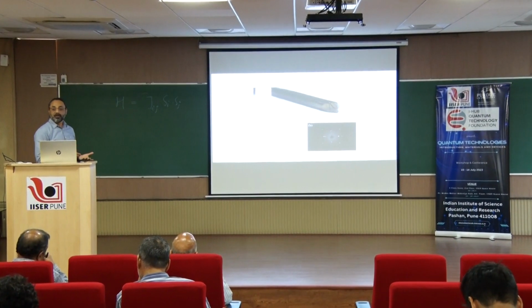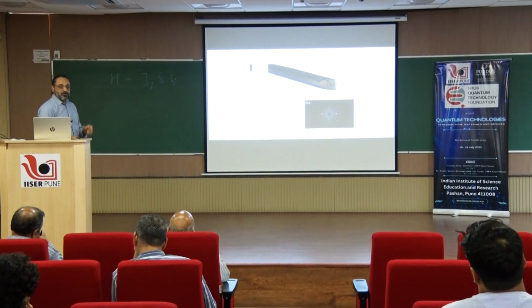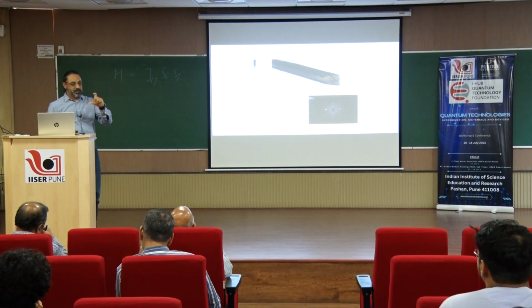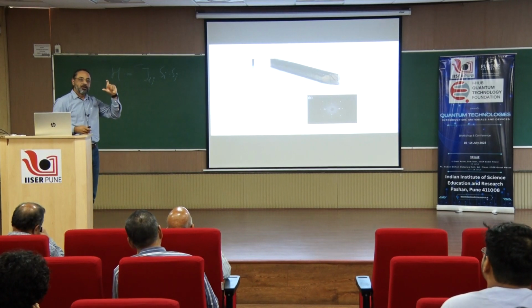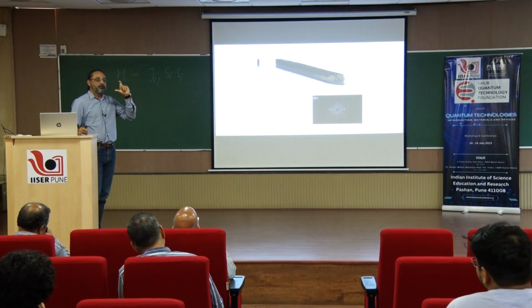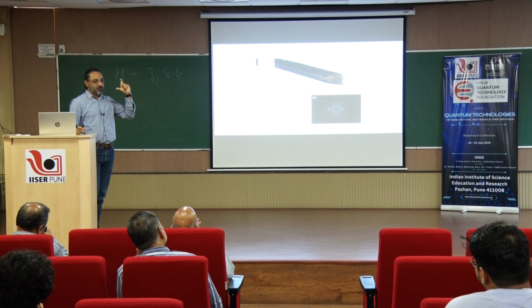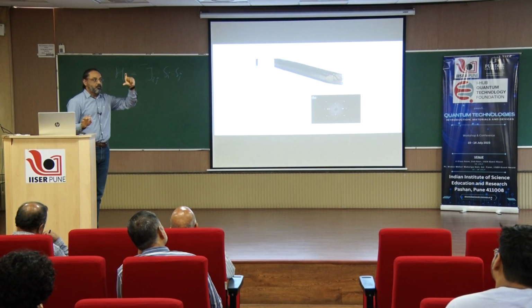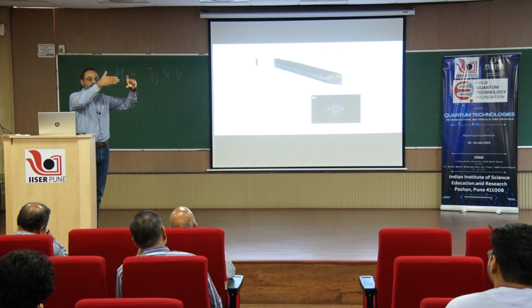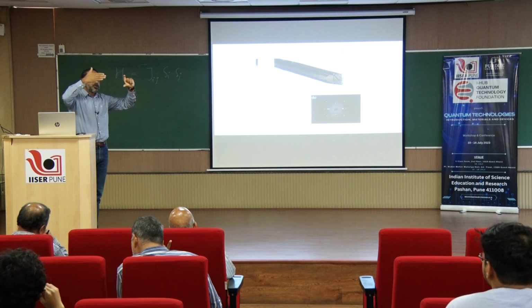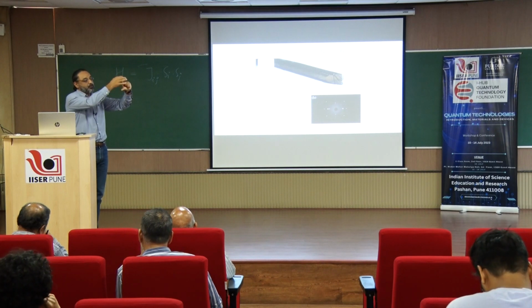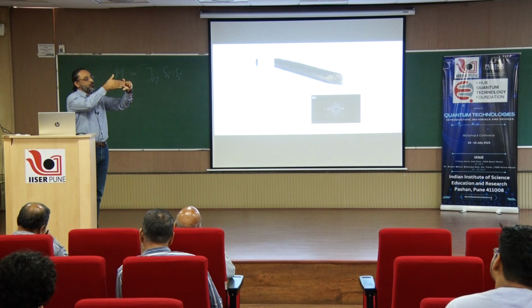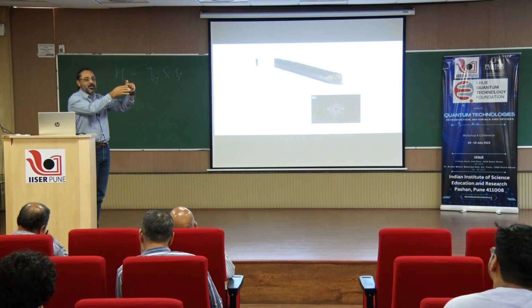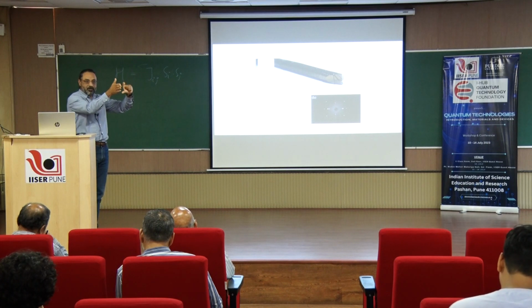This is known as rocking curve. So what are we doing here? So we have a large crystal, let's say about a few centimeter long and a few millimeter in diameter, and we want to see whether this crystal is a good crystal or not. So what we do is we place it in the path of an incoming neutron beam. Okay, this is a monochromatic neutron beam. So if in the passage of this neutron beam there is a crystalline material, then the neutron beam will get Bragg diffracted along different directions, Bragg directions.